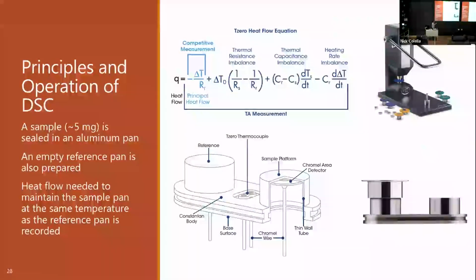So to actually run the DSC, we're going to load your sample into a little aluminum pan like this. Again, about 5 milligrams of material is generally good. We're going to seal up the pan. We can either seal all the way around the edge, or we can leave it kind of exposed to the environment so solvents can evaporate, depending on what your sample is.